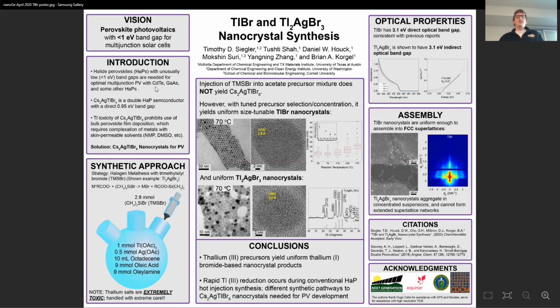However, pairing these perovskites with CdTe, gallium arsenide, and other incumbent PV technologies requires perovskites that have low, sub-1 eV band gaps, which is outside of the range of the composition space that's normally used in perovskite photovoltaics, which have 1.2 eV band gaps or higher.